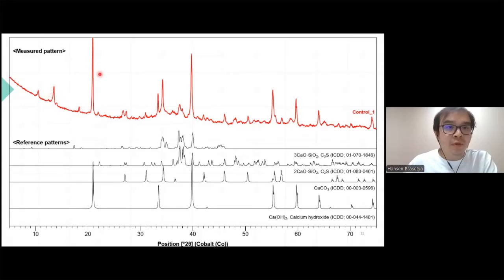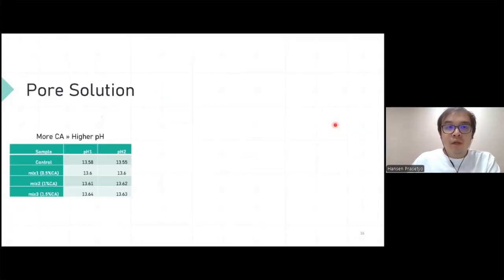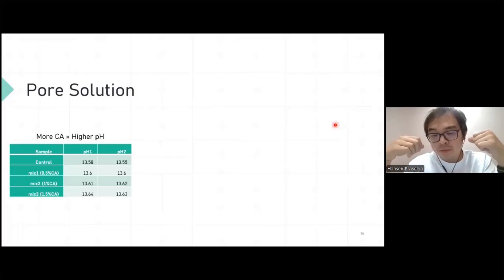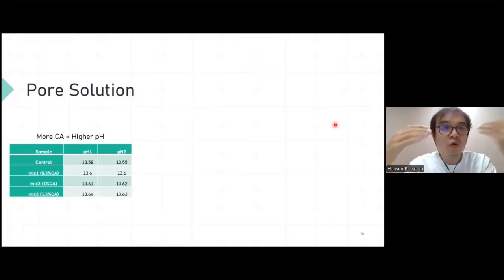The diffraction patterns are also just the usual components of cement paste. There's nothing special that appears when XRD is done on the hydrated sample. Right. So since the solid phases are very similar, we just need to check the pore solution.